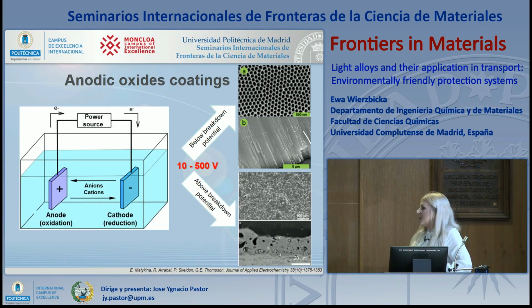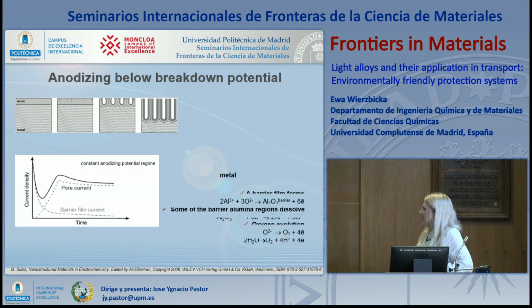The second big group of protective coatings is anodic oxides. They can be formed by a simple anodic reaction in the electrolyte, by application of an external power source. The applied voltages can be very varied. We can do this procedure under two conditions, below breakdown potential and above breakdown potential, which provides different morphology of those coatings.